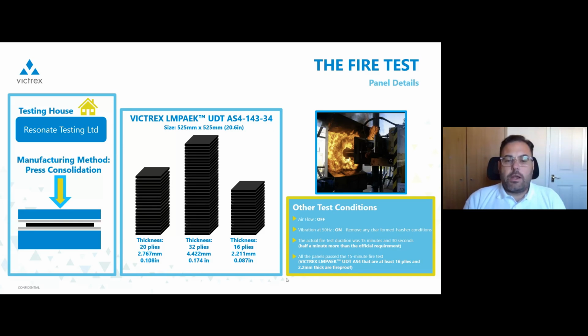And when we did our tests, we tried to do it in as harsh conditions as possible. So we decided to have airflow off. The airflow not only can cool down the back of the panel, it also removes any volatiles. That's probably more relevant with thermosets, as thermoplastics don't have the volatiles that thermosets have. And the other thing is, we also had vibration on. Vibration on the standard is around 50 hertz.